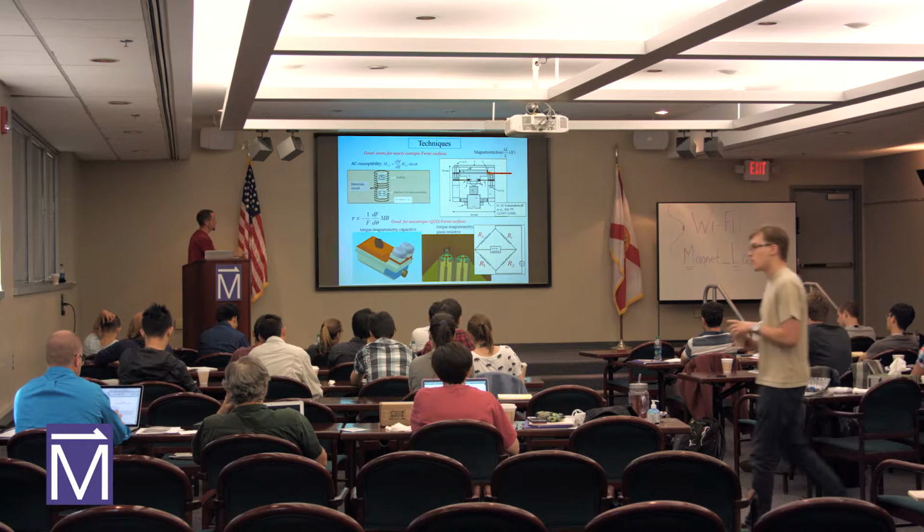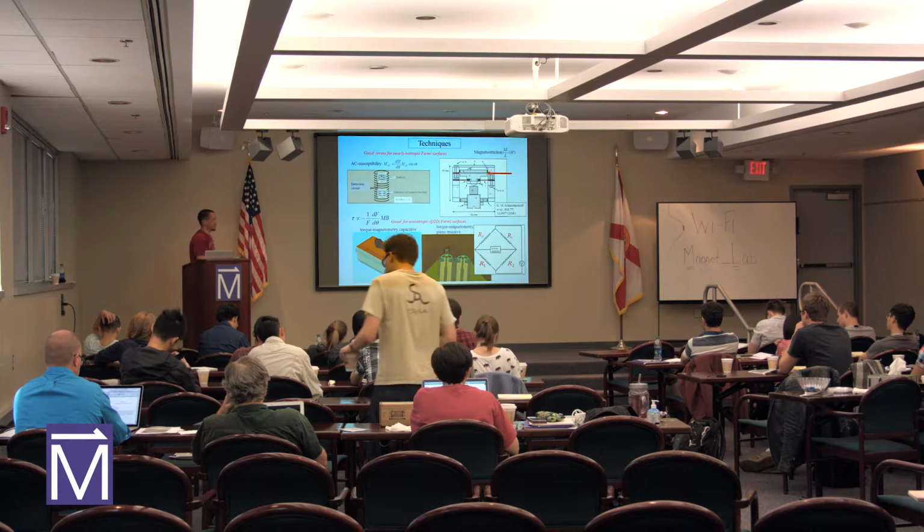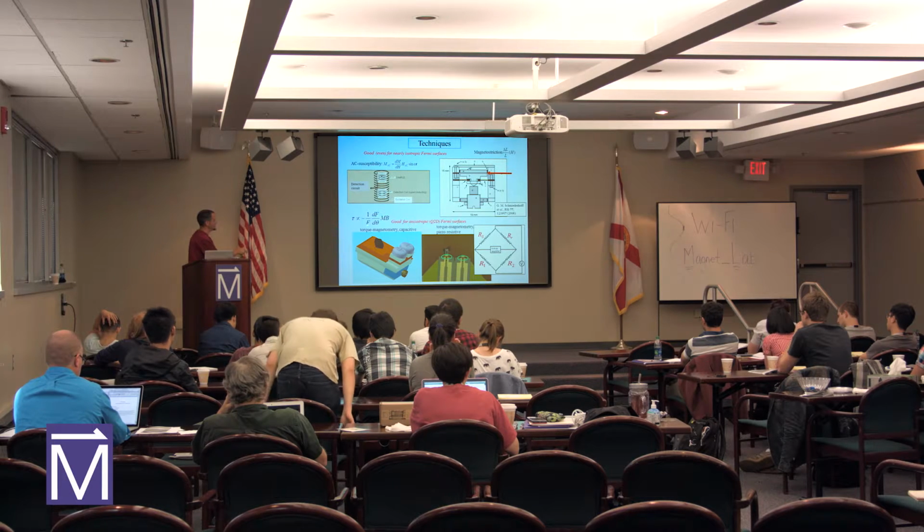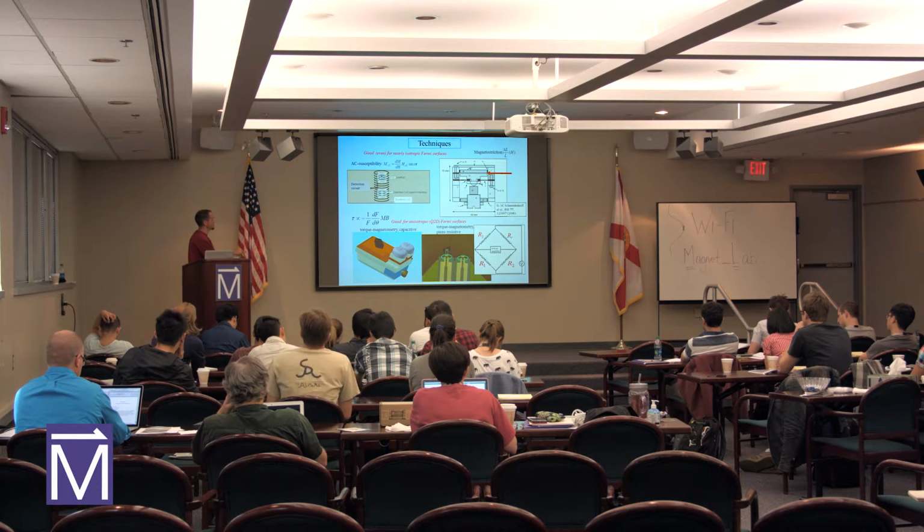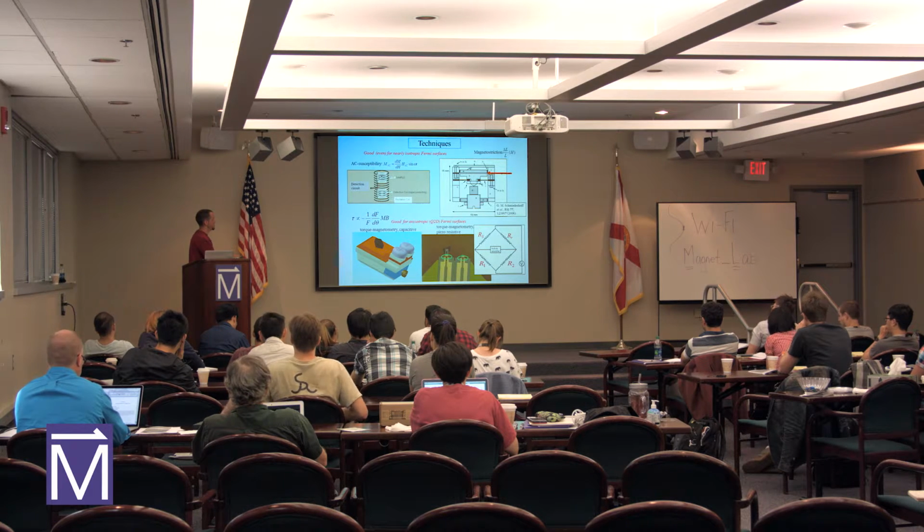But to create torque, you have to have a change in the shape of the Fermi surface. This term means that the frequency is changing with angle. So if you have a spherical Fermi surface and you try to measure it through torque magnetometry, you won't create any torque. You won't be able to measure it.